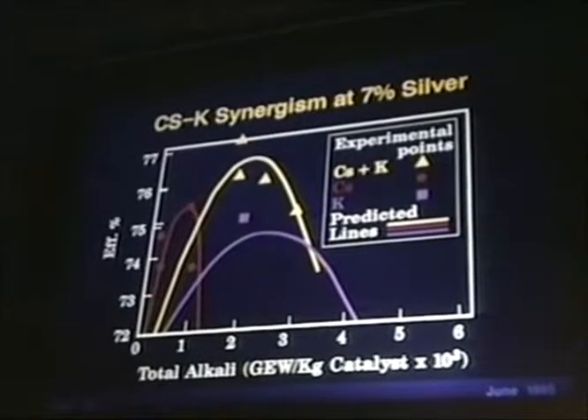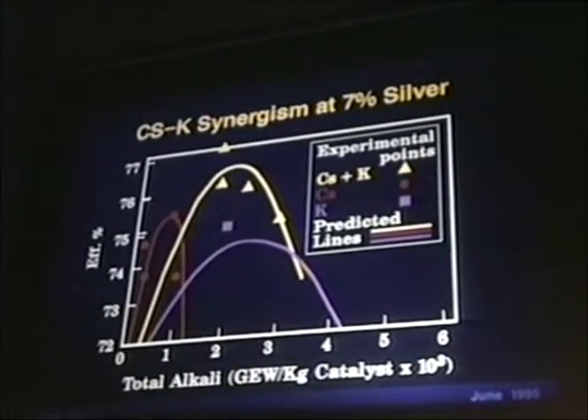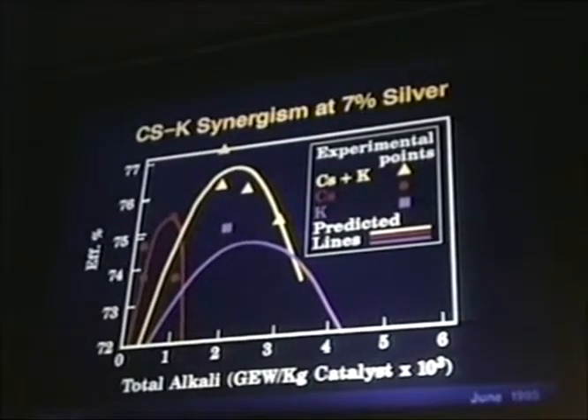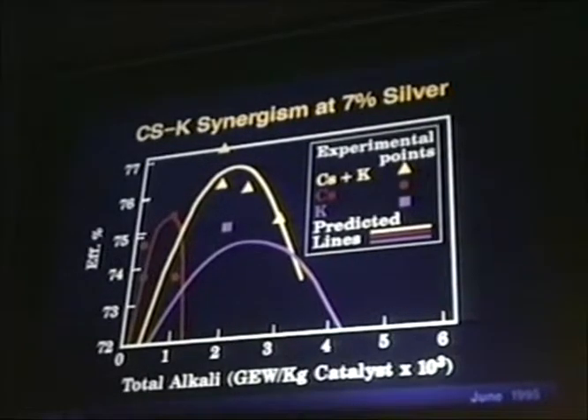Now I'd like to capture the highlights of the cesium-potassium synergism work and show you where the mixed cesium-potassium system not only performs better than cesium or potassium, but has the best of both features as well as higher efficiency by over 1%. And by the way, in the multi-billion dollar ethylene oxide glycol business, that is a lot of money. This was, as we presented, based on a very large statistically designed set of experiments. And our confidence in those predicted lines is within 0.1% in efficiency, which is better than the standard deviation of a single measurement.